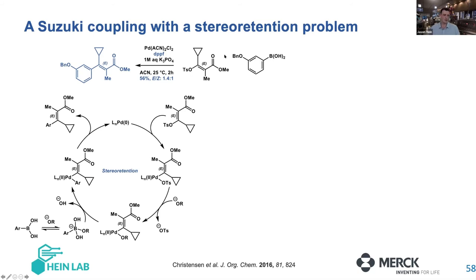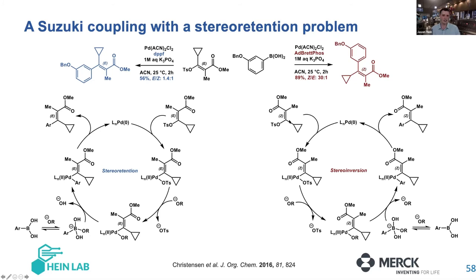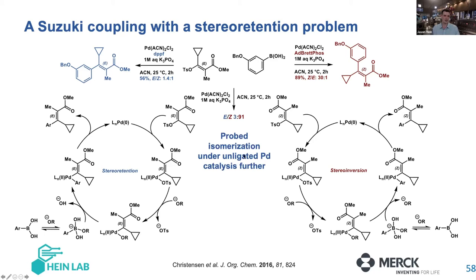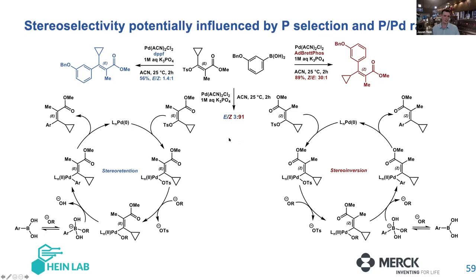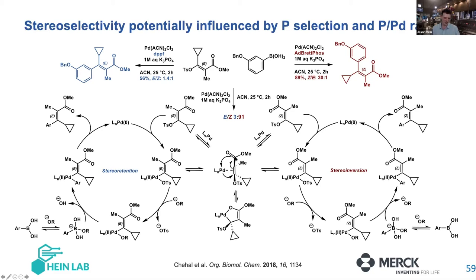Now, this is a really hard thing for this molecule because we've got this donor group over here. This carbonyl really, really likes to favor a stereoinversion pathway. If you treat these kinds of systems with palladium, it goes by way of a binding event where, even if you go in with a non-perfect ligand, it likes to go through this enolate intermediate binding here, which twists the system around and ruins the stereoretentive outcome.